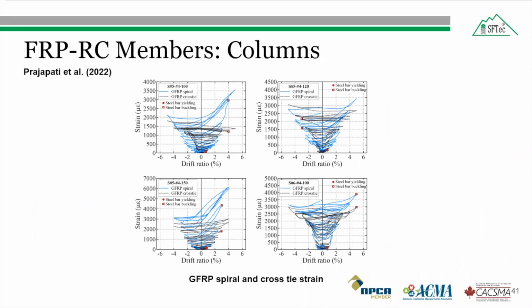We observed a non-zero strain at zero drift in both spiral and cross tie, and development of significant strain in the GFRP spiral and cross tie at the steel bar buckling. You can see here the development of a significant amount of strain, in some cases higher than 2000 microstrain, and 2000 microstrain is generally the yield strain of steel bar. The confinement effectiveness of steel ties beyond 2000 microstrain was generally found to be insufficient, whereas the strain developed in the GFRP spiral and cross tie went beyond 2000 microstrain and provided effective confinement until the failure of the specimen.